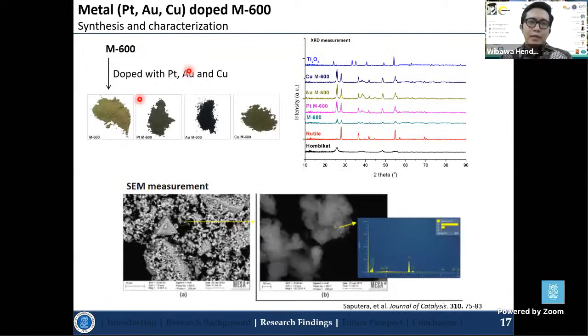And it seems that the platinum is actually successfully deposited in the M600, but we cannot see any additional peak based on the XRD compared with the parent rutile and the anatase. So it means that the metals are successfully deposited and distributed homogeneously in the titanium dioxide TiO2 mixture particles.